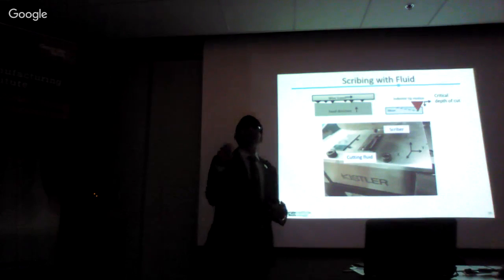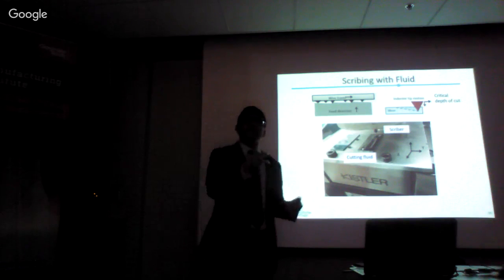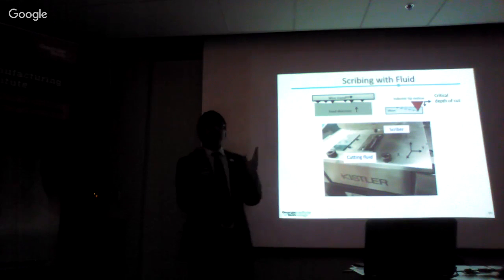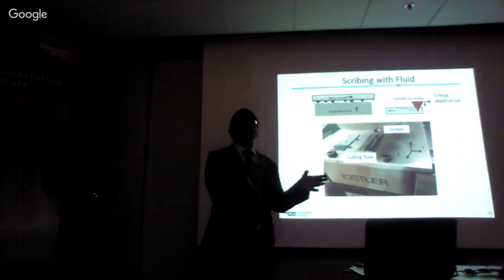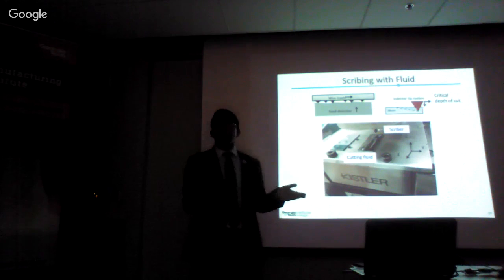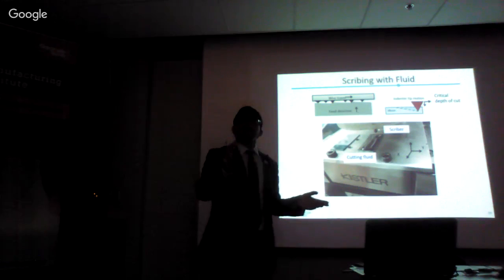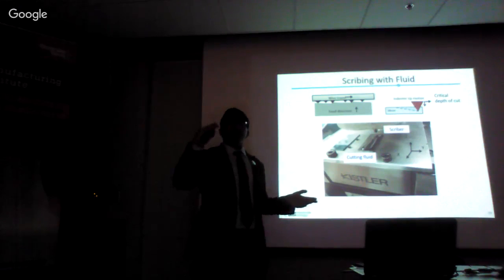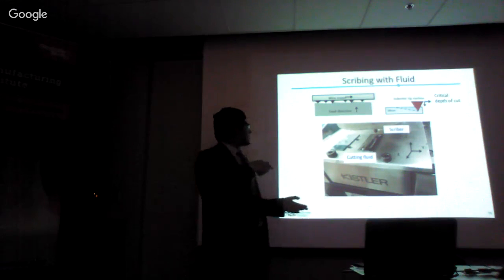So we are simulating the wire sawing operation in industry by the scribing process, and in this experiment again we use the increasing depth of cut scribe, because our objective is to find if using the cutting fluid gives a more ductile mode material removal compared to using dry conditions. So we want to compare the critical depth of cut, which is the depth at which the first crack appears.